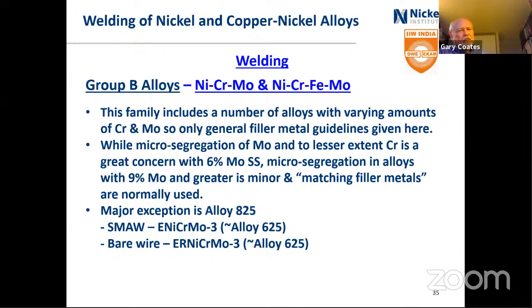So when we come into the nickel chrome molybdenum and the nickel chrome iron molybdenum, which are like the 625, 825, C type alloys, there is a lot of different variations of them. So if you think of the 6 molybdenum stainless steels, the 254 SMO, AL6XN materials, you're really worried about the microsegregation of molybdenum, which is why they are welded with a high nickel filler metal. Well, when we get to the high nickel alloys, such as 625 and the C alloys, that's not a problem, not a major problem anyhow.